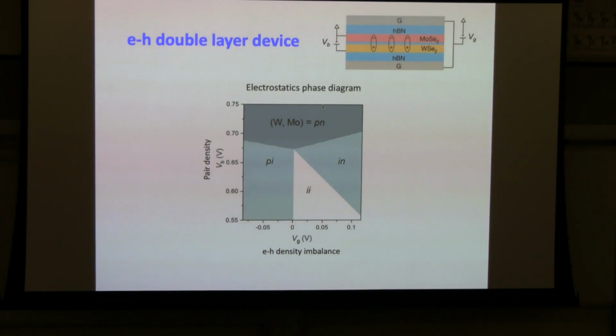So this is the double layer structure. As I mentioned, we have 2 parameters that can tune the system. One is the interlayer bias voltage, VB. The other is the gate voltage, VG here. By just knowing the thickness of each layer individually, which we can measure, for instance, with atomic force microscope, we can immediately simulate the electrostatic phase diagram of this double layer, which is plotted in this way.